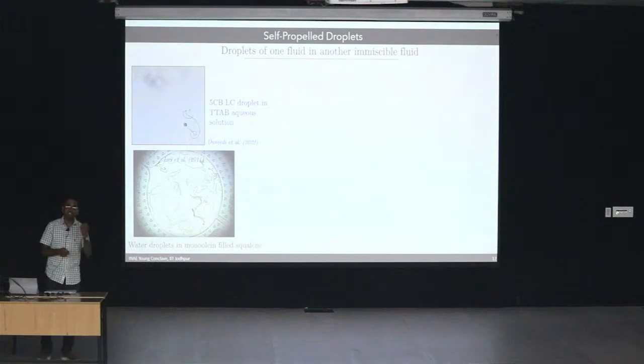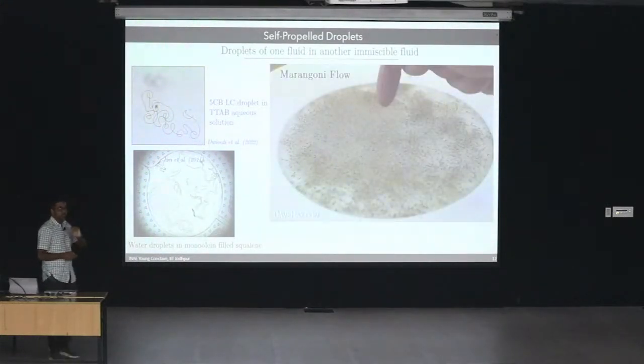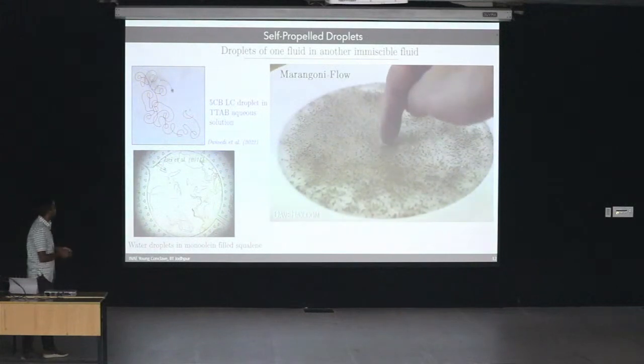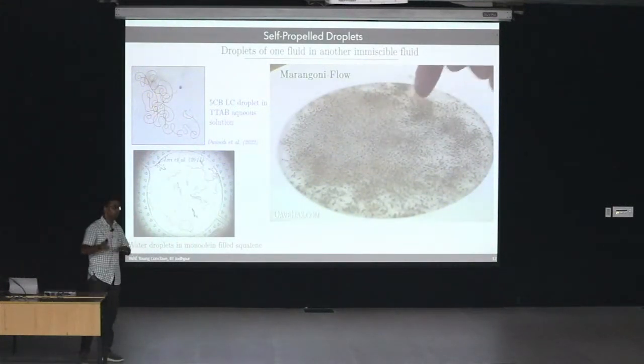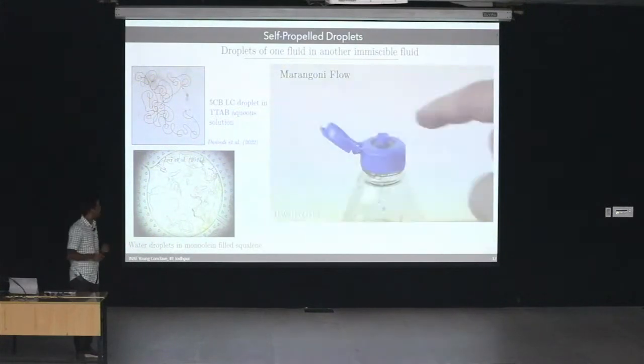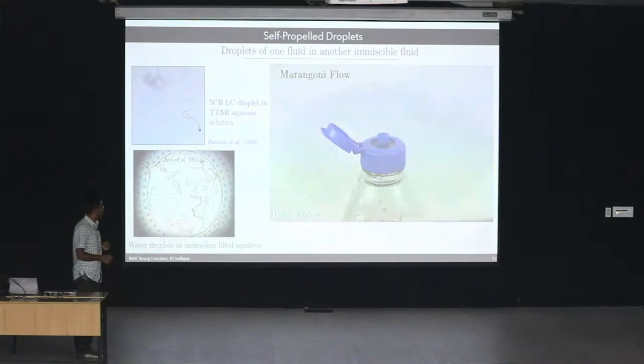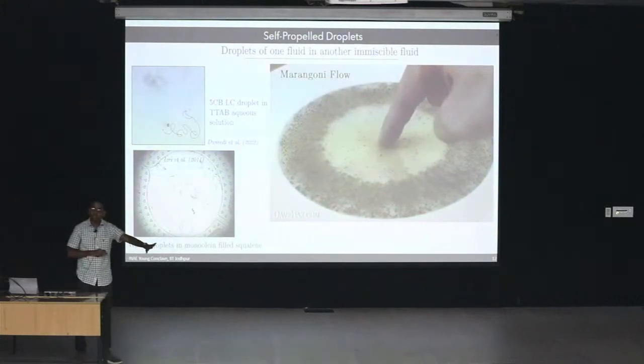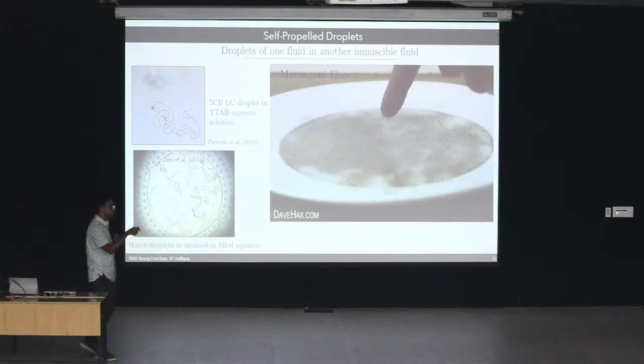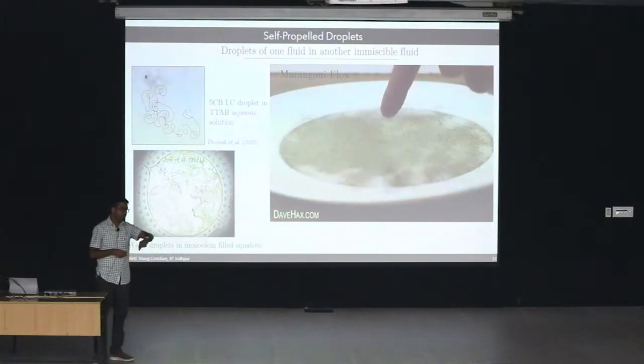Similarly, we can create artificial droplets as well. So these are droplets of one immiscible fluid in another immiscible fluid, and they also perform very nice active motion. I will not go into the details of their propulsion mechanism, but very quickly, what we use is Marangoni flow. If we have a surface of water with black pepper spread on it, if we touch it with our naked finger, nothing happens. But if we apply some soap and then touch it, we'll see a radial flow in the outward direction. And that is simply because when we put in some soap solution, we are adding surfactant to the system. Surfactant decreases the surface tension. So at the point where we have touched, surface tension has gone down, and outside the surface tension still remains high. That generates a flow which is known as Marangoni flow.